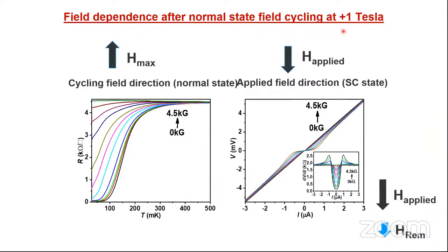And in this case, because now this is being added to the remanence, which is in the negative direction, these two are in the same direction. There is no non-monotonic dependence of the critical temperature on the magnetic field, but with increasing magnetic field, the critical temperature goes down systematically and disappears at 4.5 kilogauss. And the same thing happens for the critical current as well.